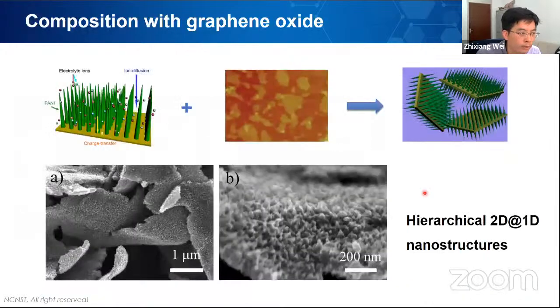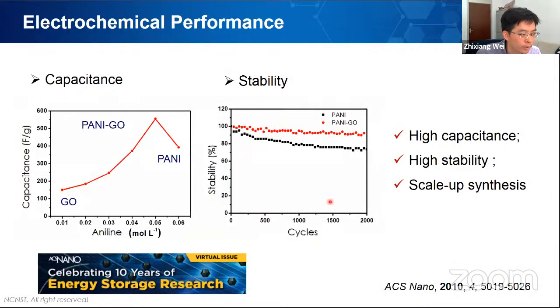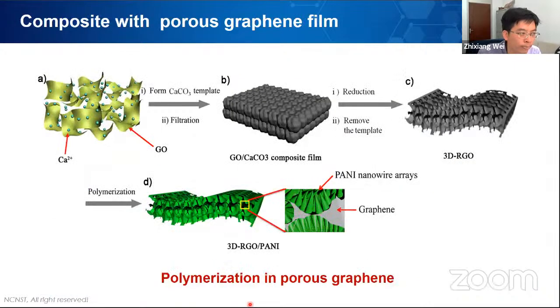is easy. Just mixing the aniline monomer with the graphene oxide in solution, by oxidization, you can get this kind of structure. This was actually selected as one of the 10 most important papers in ACS Nano in their 10 years celebration. And how can we really make a flexible device using this kind of nanostructure?